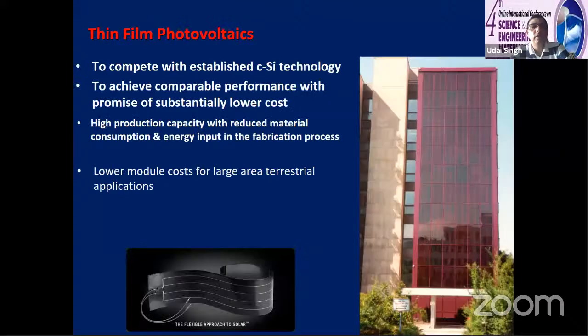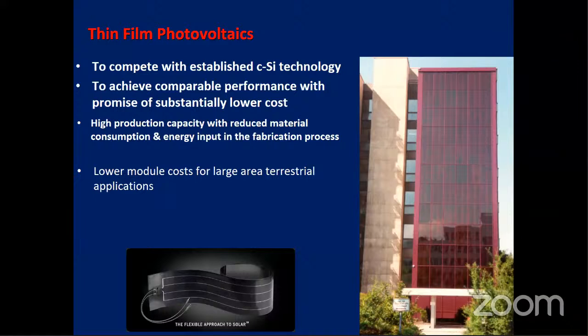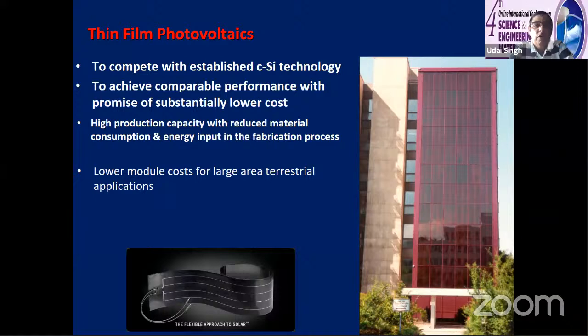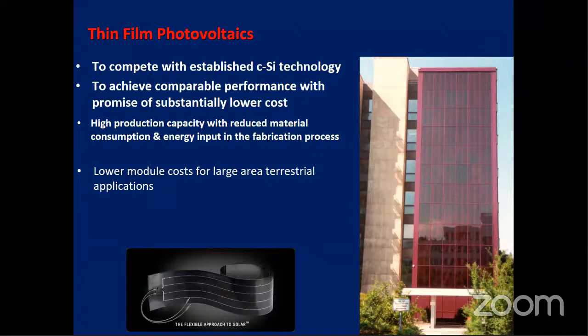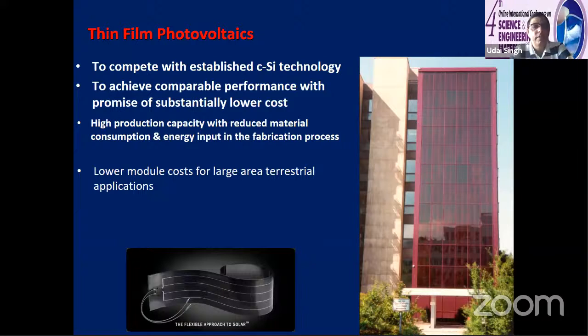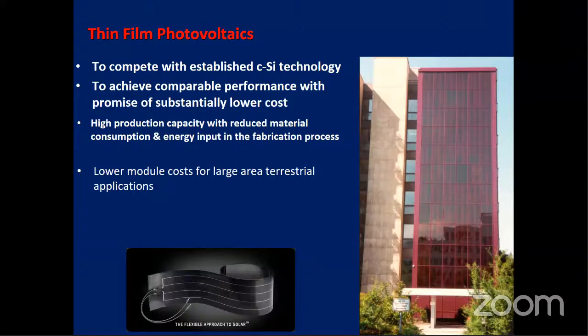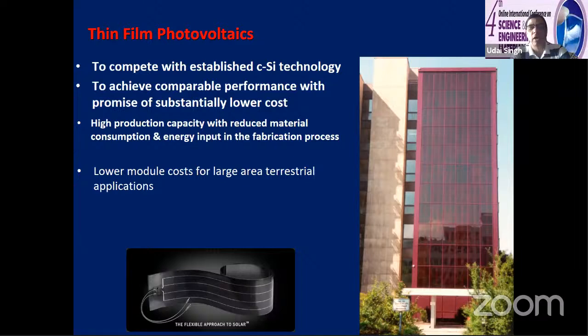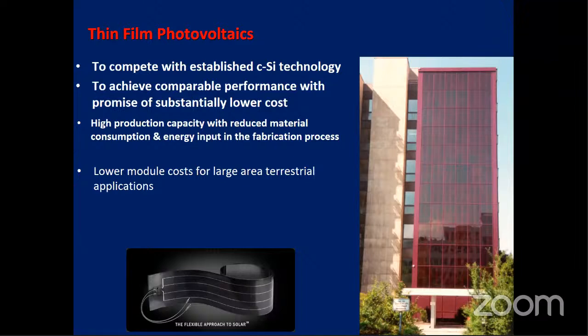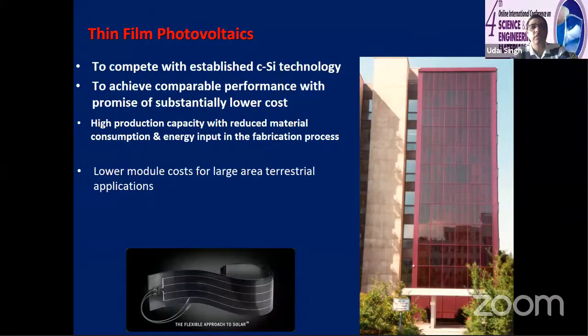If one looks for thin film photovoltaics, it has to compete with the established crystalline silicon to achieve comparable performance with the promise of substantially lower cost, and high production capacity with reduced material consumption and energy input. Another is the energy payback time. Energy payback time for silicon is around 3 years, that is, how much energy you consume during production and how many years it takes to recover that. For thin film, mostly it's around 1 year.